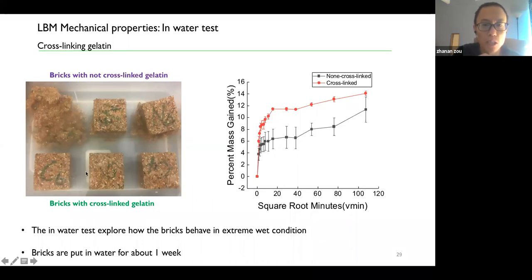Those without cross-linked gelatin at about 1 week have already shown deterioration, or the shape has fallen apart, while the cross-linked ones still maintain their cubic shape. At the same time, we also kept track of the mass gain. As you can see on the right side of the figure, we kept track of the mass that they gain with respect to time. The black curve represents the one with the non-cross-linked gelatin, while the red curve is the cross-linked gelatin.